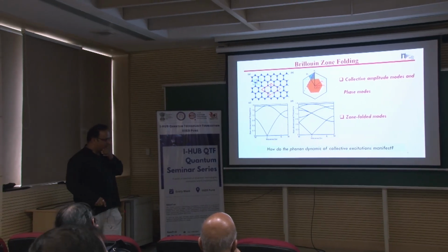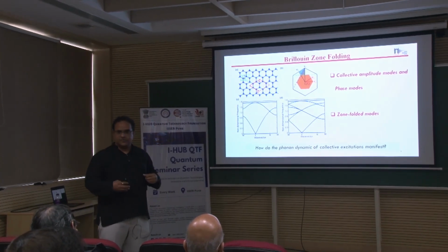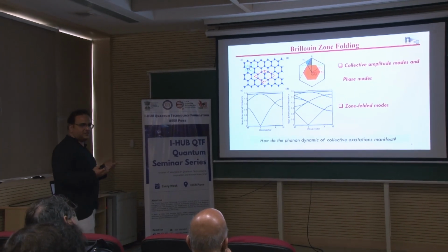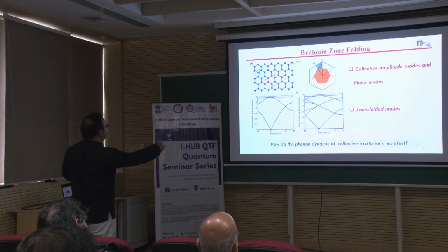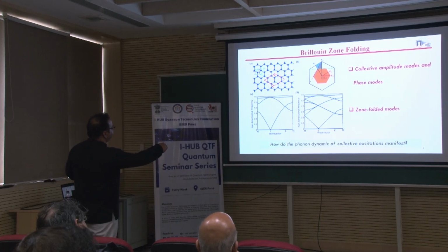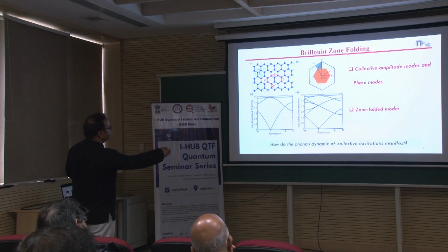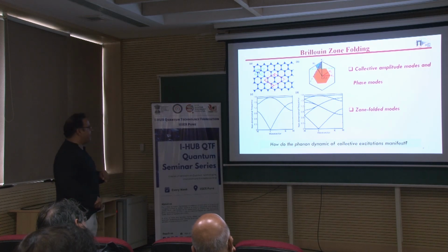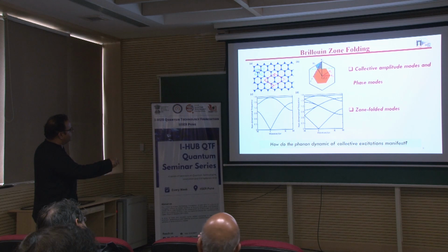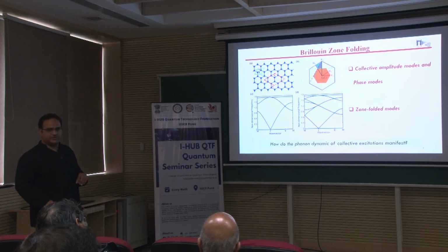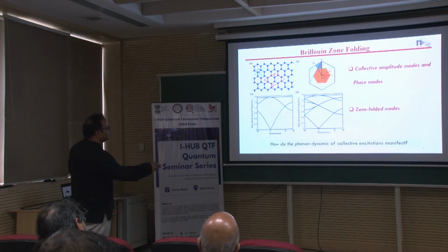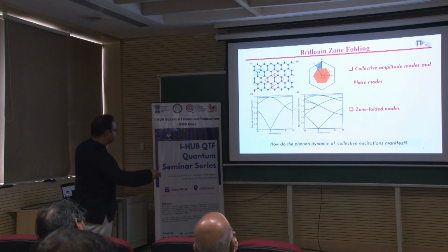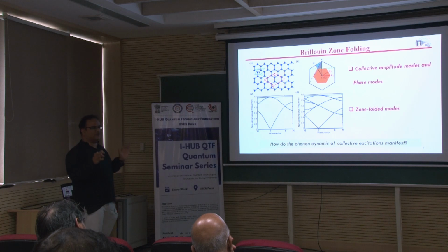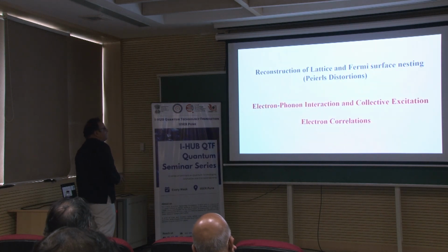All right. Now, when I say that there is a folding of the Brillouin zone, you are breaking the symmetry, so you may expect some new phonons to come up. For example, this is the primitive cell for the undistorted lattice, represented by A1 and A2. Now, this is the new one. So now you see the Brillouin zone which was like this one is half of that, and right at the boundaries you will have the gap. If you look at the phonons, this is the original lattice and this is the charge density wave. So, you have new modes which are coming up, and these modes are called the zone-folded modes because they come from the folding of the Brillouin zone. So, you have the collective amplitude modes, phase modes and the folded modes. These are the modes I am saying, these are the super modes. But how do we observe them, that I will take up.